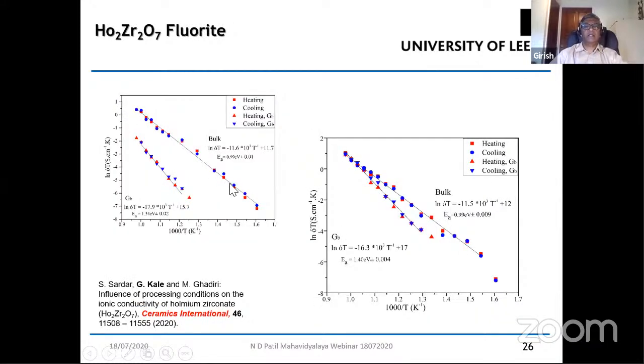Now, the interesting thing, or the uninteresting thing, is that it is not very unusual. So we haven't got the conductivity even anywhere close to yttria stabilized zirconia. So what can we conclude from this? What we can conclude is that this material, in its current form, is no good for using as the solid electrolyte.